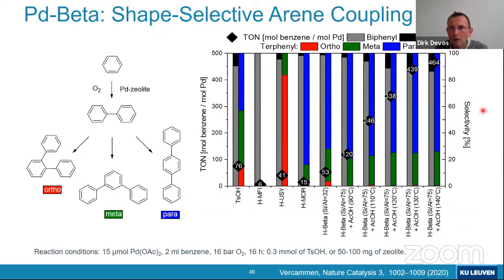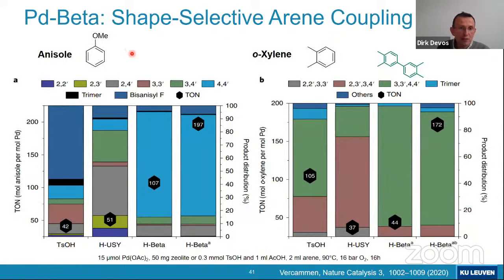So that's the blue bar here. So you see that also in this production of compounds like terphenyl, you get a very considerable shape selectivity. And that also holds for instance for anisole. In the case of anisole, we get again a very high selectivity for the para-para product, the 4,4', which is the light blue bar here.